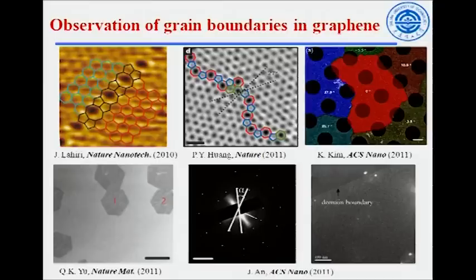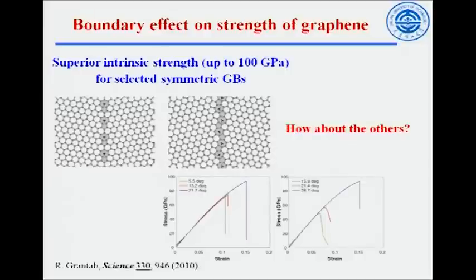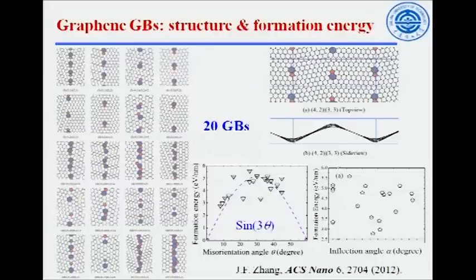So the question is, how about the others? Because as we can see, there are so many kinds of grain boundary, almost infinite possibilities. What will be the systematic trend in addition to these selected symmetric boundaries? We have done some more systematic work, and we built a structural model, and we considered up to 20 grain boundaries of different kinds of possibilities. First, we look at the formation energy as a function of misorientation angle and inflection angle.